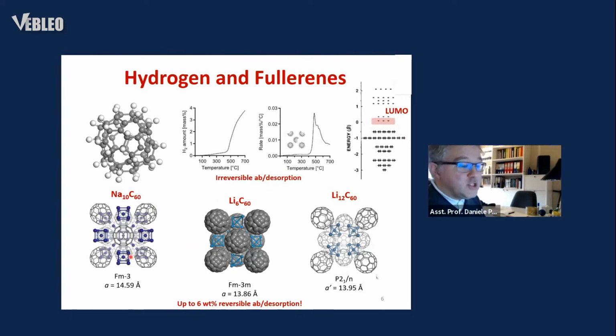In particular, we managed to isolate some alkali cluster intercalated fullerides, where alkali ions form small clusters inside the octahedral voids of the crystal, which turn out to be able to absorb up to 6% of hydrogen at moderate pressure and temperature conditions, and very importantly, in a reversible way.